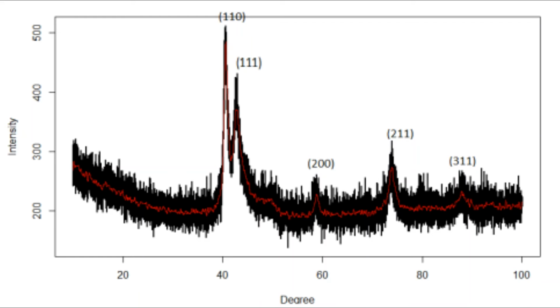The XRD spectrum shown here is for an aluminium, copper, iron, molybdenum, nickel high entropy alloy sample that had been milled for 20 hours. From the peaks present, it can be determined that at least two phases had formed, that these peaks indicate that at least a BCC and an FCC phase had formed. Most of the peaks present correlated to reference peaks of elemental molybdenum and copper, with the peaks of the BCC phase corresponding to the peaks found for molybdenum, and the peaks for the FCC phase corresponding to those of copper.